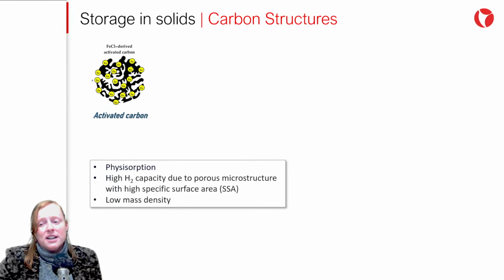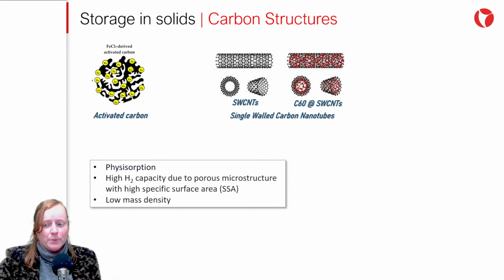Activated carbons. These are carbonaceous materials with a large surface area and an internal structure composed of a series of pores and cavities. Activated carbons are obtained from materials such as coconut shells, wood, charcoal, or coal through an activation process involving thermal and/or chemical treatments. Carbon nanotubes. Discovered in 1991, they drew a lot of attention as a promising material for hydrogen storage applications. Nanotubes undergo treatment to make the inner part accessible for gas penetration and to increase the accessible surface area.